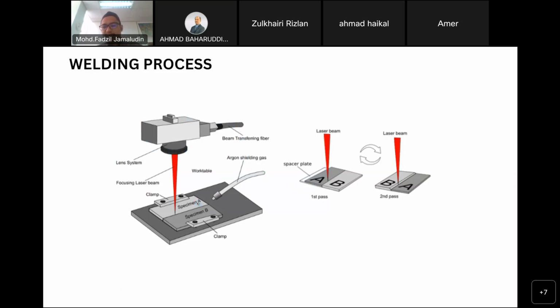In our case, because we had some studies before, we are proposing what we call a double-sided weld. Because of the low power, we found out that the penetration depth cannot achieve what we desire. So we proposed that the weld can be done in 2 passes, meaning that you do 1 pass, and then the specimen is turned over, and we do a second pass using the same parameters on the other side of the specimen.